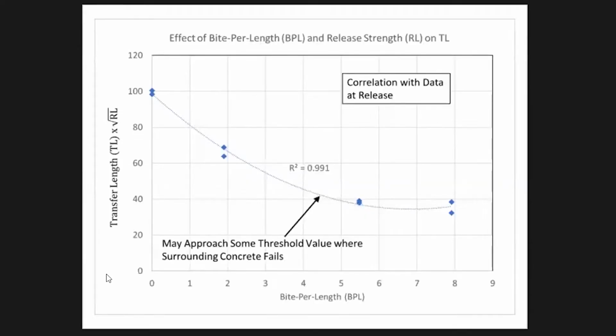So here are the 8mm wires. On the left axis, I have the transfer length times the square root of release strength. And on the horizontal axis, I just have the parameter bite per length. And you can see when we use transfer length times square root of release strength, these two points, the same wire at different release strengths, come together. I just did a parabolic curve fit because I'm not really that good at Excel. That was just quick and dirty. Dr. Terry Beck is doing the correlations on these, but you can see the values come down. And at some point, it appears there's not much decrease in transfer length with increasing bite per length.